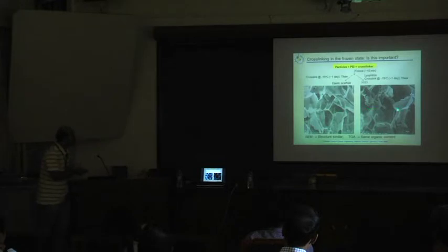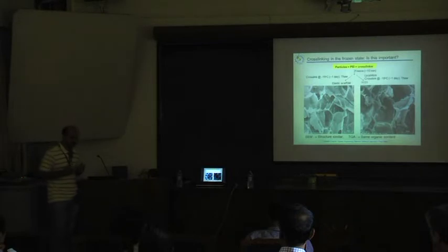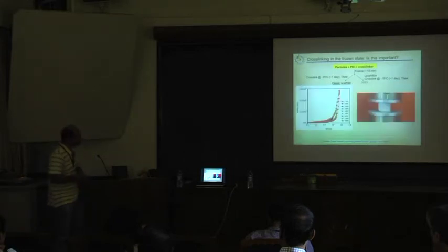So if you look at SEMs of these, the two materials look similar. We've burnt off the organic, and the organic content is the same. The degree of cross-linking that happens in both these situations is the same. So as far as chemistry or spectroscopic tools that are available to me can tell, these two materials are identical. Right. So again, just to remind you, this is what we got.